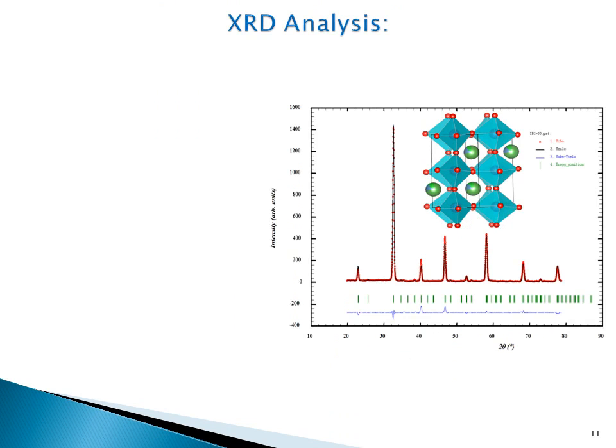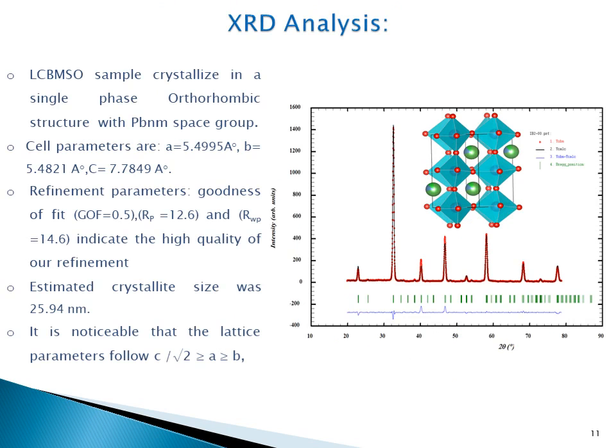For the results, firstly we start with XRD analysis. The XRD pattern of the prepared sample, taken at room temperature, is shown in the figure on the right. According to the Rietveld refinement, using FullProf software, the sample exhibits a single-phase orthorhombic structure.